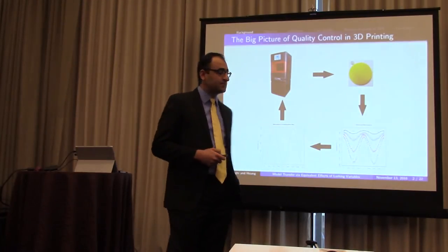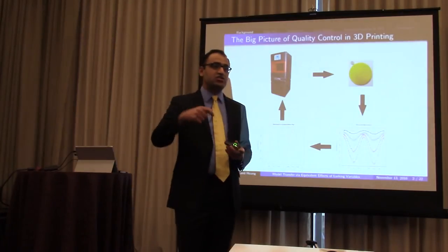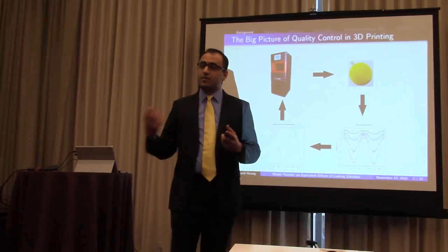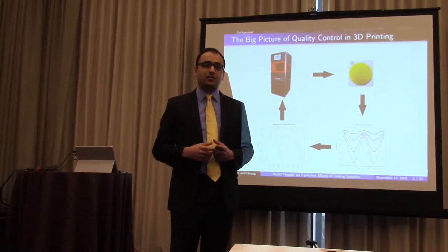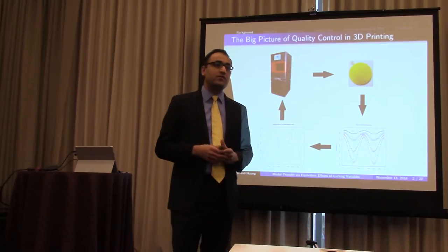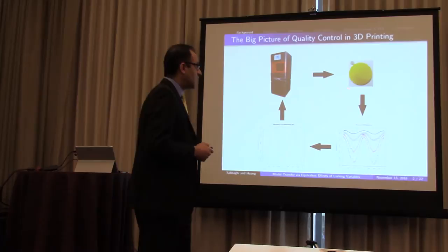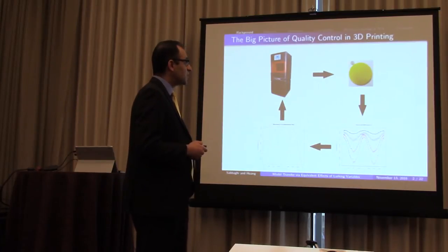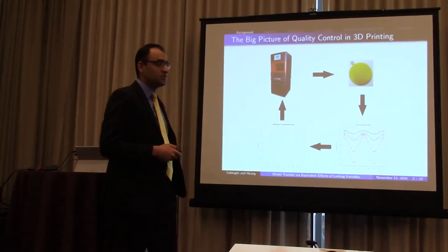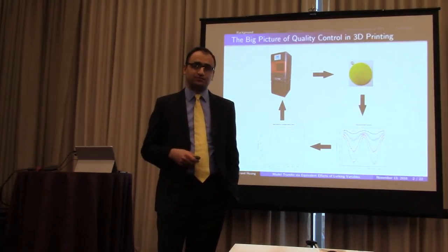these products. And from such a model, you could predict deformation and see how to change the original computer-aided design model, basically add or subtract material on the boundary of the shape to form a new CAD model so that when that deforms, it deforms into the shape you want, a circle. And we've achieved some measure of success with this strategy. For example, when we started printing the cylinders in 2012, by adopting this strategy, by implementing a compensation plan to the computer-aided design model, we could reduce deformation by one order of magnitude.